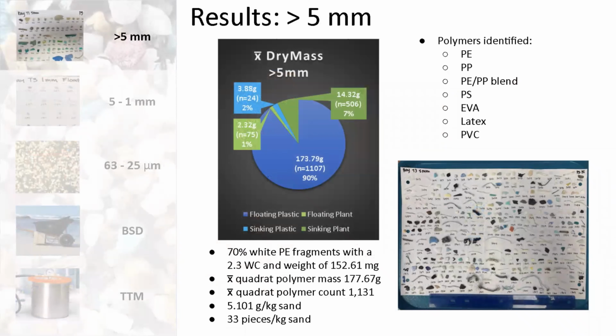So for that greater than 5 millimeter size category, we were able to identify 7 different polymers in that chamber, and analysis showed that 70% of them were white polyethylene fragments with a 2.3 weathering code and an average weight of 152 milligrams. Our mean quadrant polymer mass, so just synthetic material, just plastics that were in there, was 177 grams and over 1,000 plastic pieces. And that's the mean count again. There is 5.1 grams of plastic per kilogram of sand and 33 pieces.